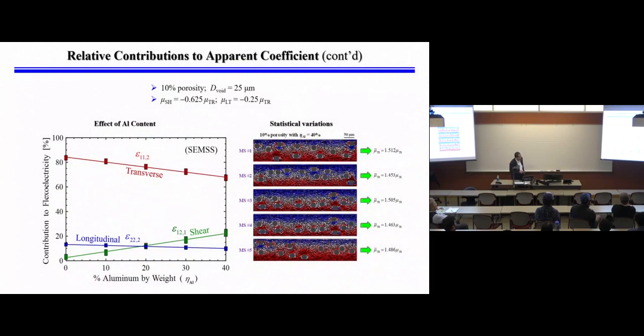Now, with different amounts of aluminum, the contributions of the three parts change. The baseline strain gradient actually decreases as you have more and more heterogeneities. With more aluminum, for example, the baseline strain gradient has less and less effect. And then the other components can increase, primarily the shear. You induce more shear. And then the longitudinal also decreases a little bit, but you enhance the shear contribution.